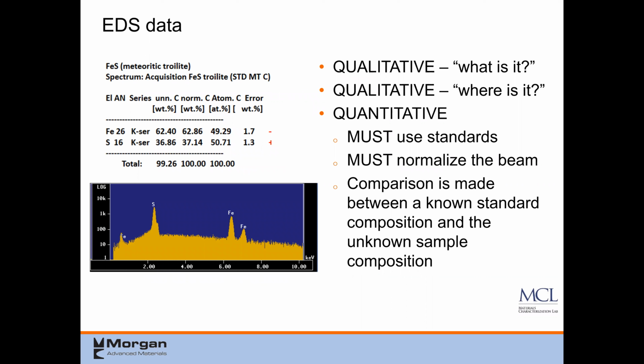On the left, you can see an example of an EDS spectrum. As you see, there are 4 peaks shown there, 3 of which correspond to iron and 1 of which corresponds to sulfur. And you get an idea of what it is. So EDS is more qualitative. It's telling you what it is and where it is. If you want it to be quantitative and you want to know exactly what the stoichiometry is, you have to use standards and normalize the beam. Comparisons are made between known standard compositions and the unknown sample composition.